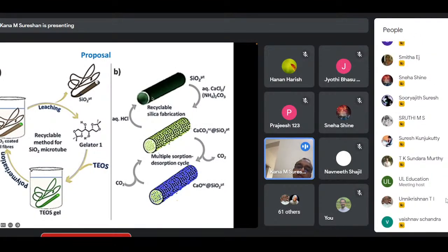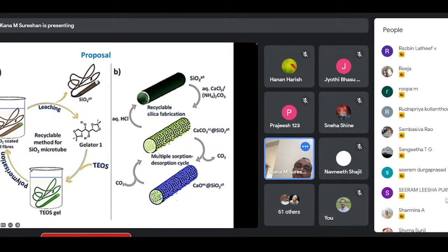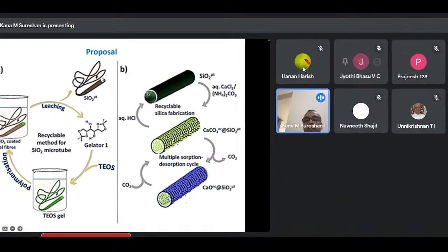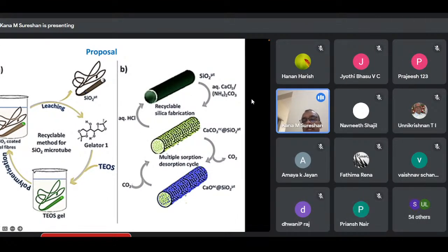So then you can grow crystals of calcium oxide on the surface. Since it is already micrometer domain, whatever is inside will be nanometer domain. So you can make nanocrystals of calcium oxide. And that will have much more surface area. And that can be used for absorbing carbon dioxide.